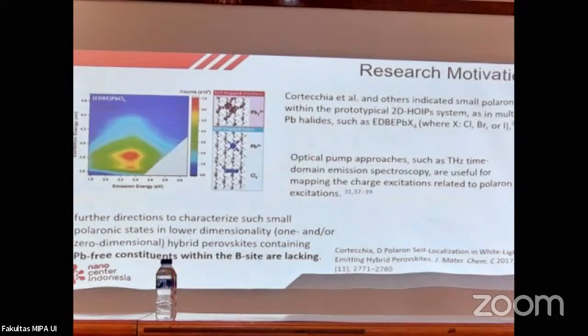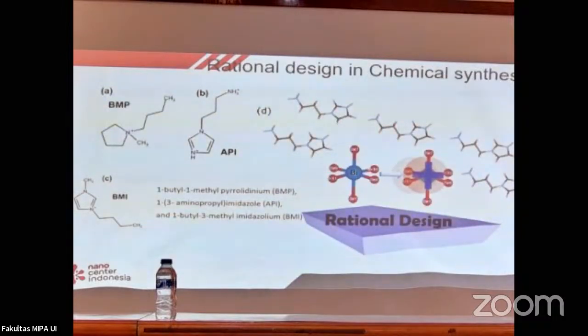Okay, so it all started with two works from Cortecchia et al. back then, and also some work in optical pump spectroscopy. We also have some interest in understanding polarons. From Cortecchia et al., it was said that for the lead halide base, we find that this prototypical 2D hybrid perovskite has some indication of the existence of small polarons. So all of this doesn't really survive that long. It takes a lot of effort, for example using very advanced terahertz time domain spectroscopy, to really get direct evidence of the charge excitations. So that is what we use as our baseline for how to continue our research direction, to demonstrate a polaronic state in low dimensional order. Therefore, we work with these three nice monomers.